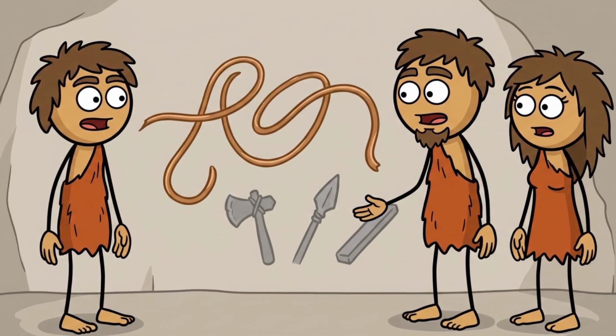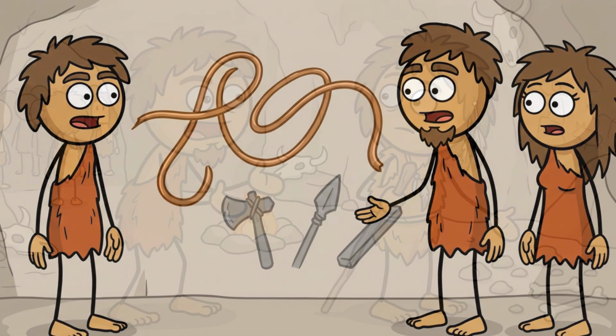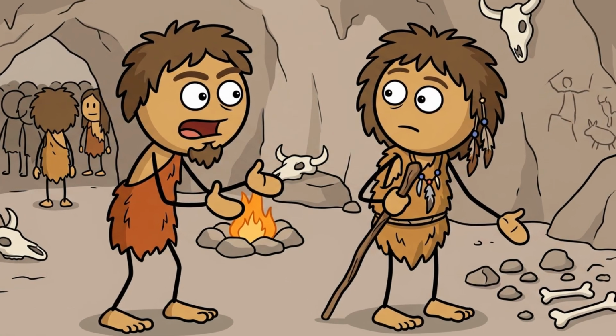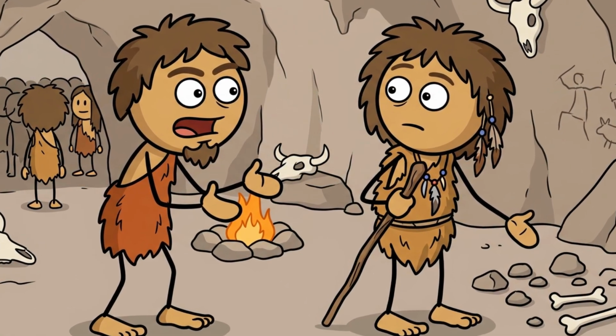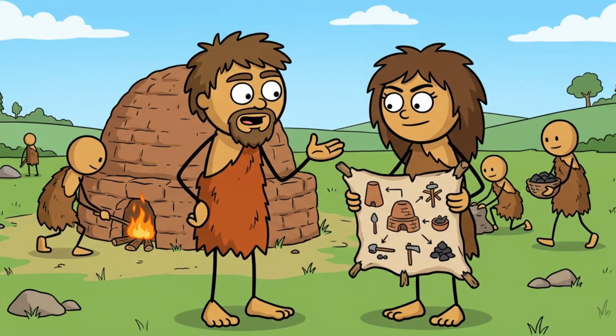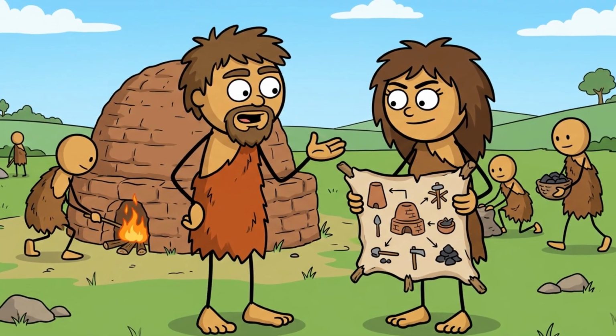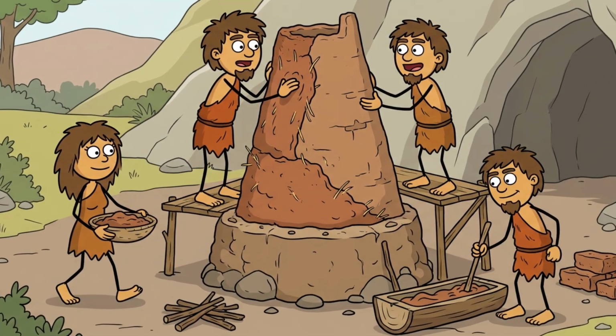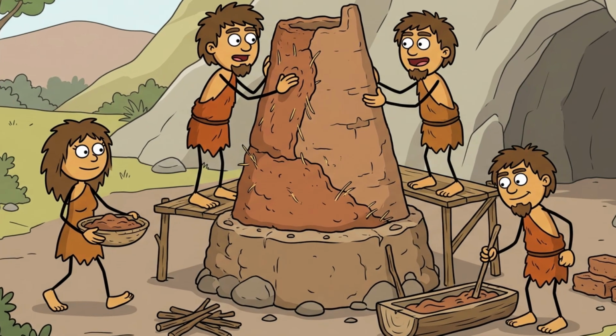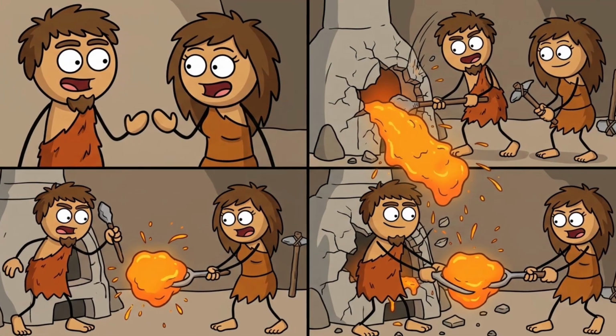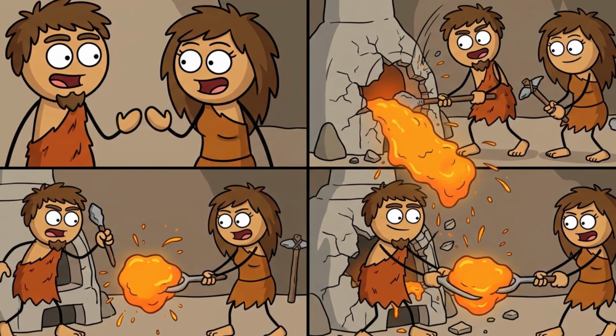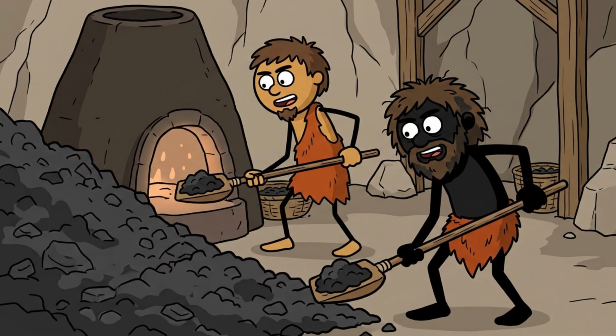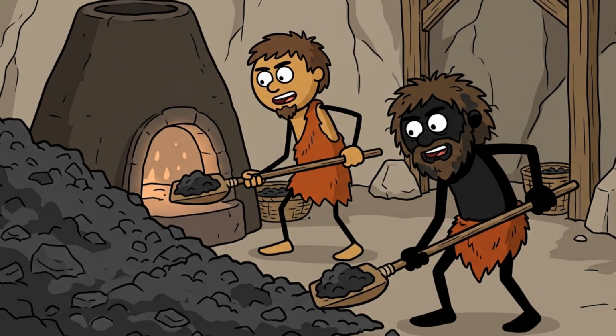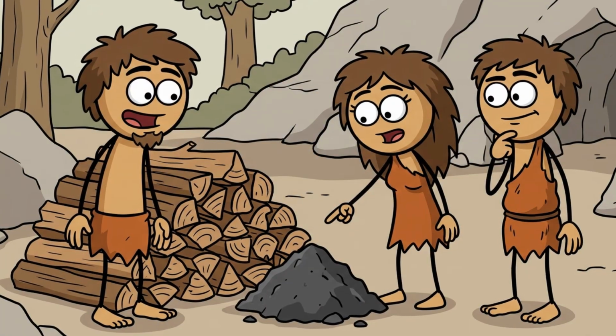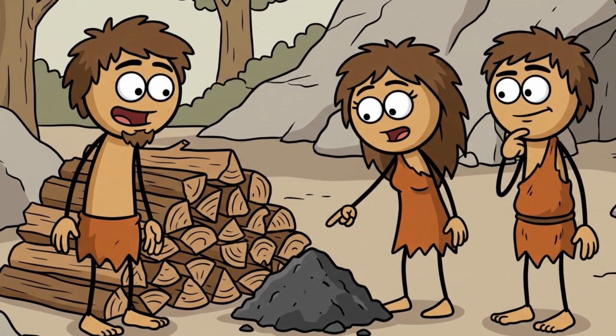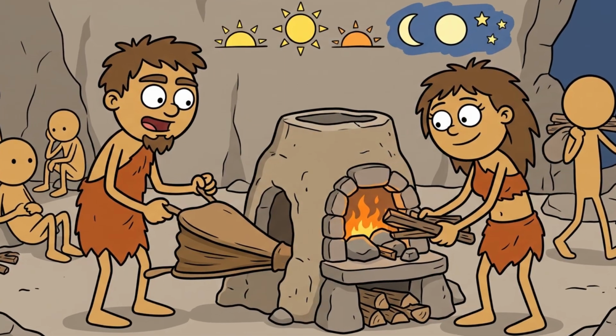And we can put numbers on exactly how hard the alternative was, because people have rebuilt these furnaces and run them. Experimental archaeologists have fired reconstructed bloomeries hundreds of times now, and the arithmetic is brutal. A single smelt takes a shaft furnace roughly 1.5 meters tall, built from clay, which often has to be broken open to get the bloom out and then rebuilt. It needs somewhere between 20 and 40 kilos of charcoal for a run of 8 to 12 hours. Producing that charcoal takes several times its own weight in wood and about a week of separate work.